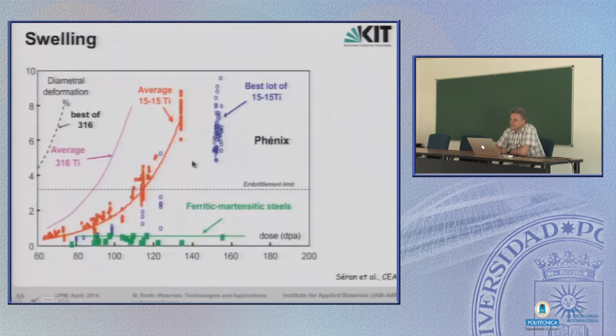And this has been compared with different alloys of the 316 steels. This is the classical steel, which swells in the range of, well, more than 6 or 8% at around 70 dpa. But another type of austenitic steel has been produced with more and more tiny and fine titanium carbide precipitates. And again, remember, precipitates are also sinks for these vacancies and interstitial recombination. You can consider them as recombination centers. And so if you produce a material with many finely distributed precipitates, this affects swelling in a positive way, since this reduces the swelling behavior.